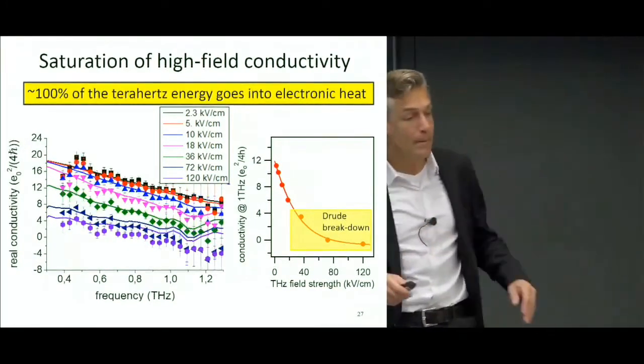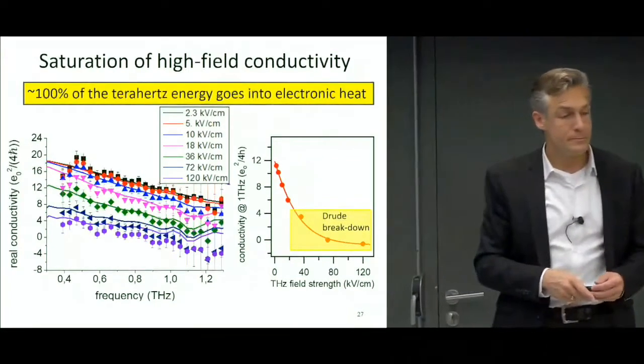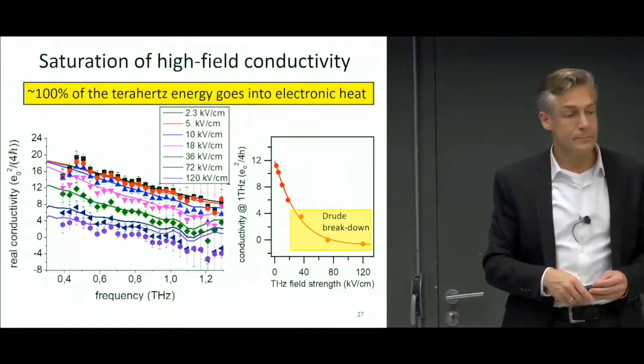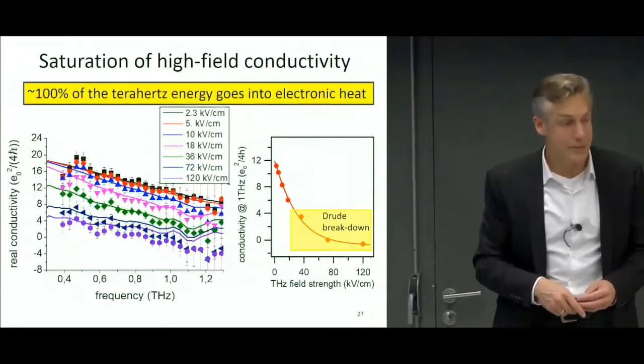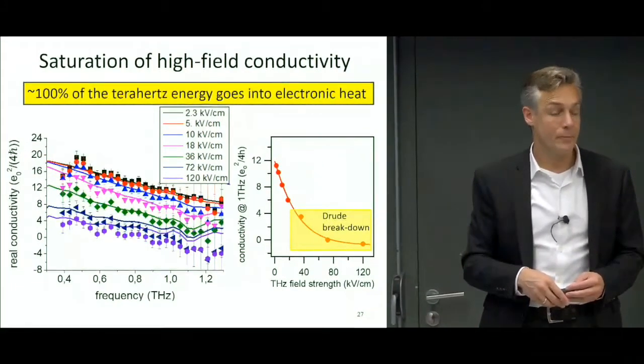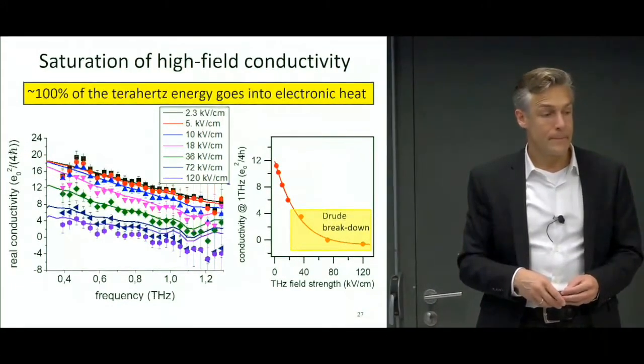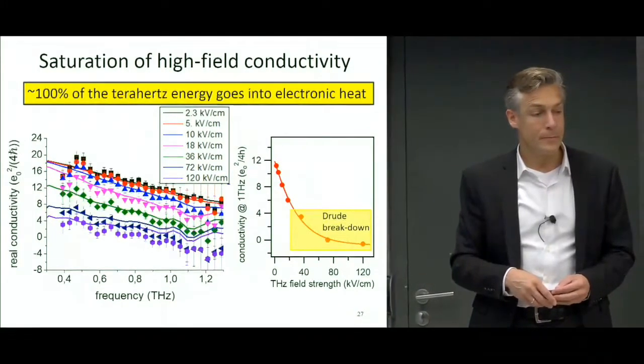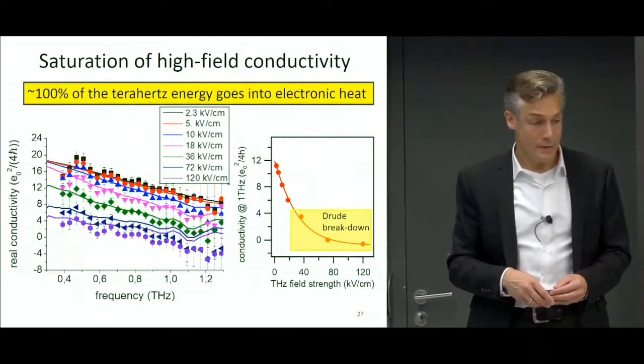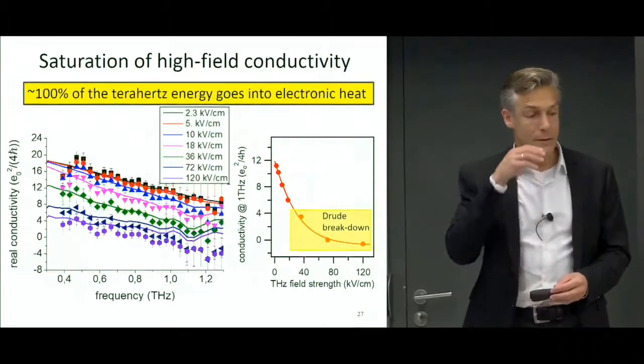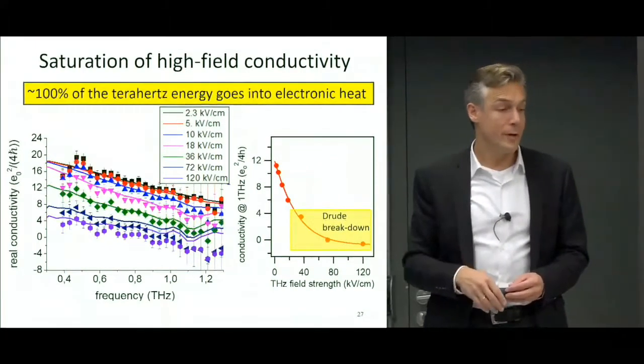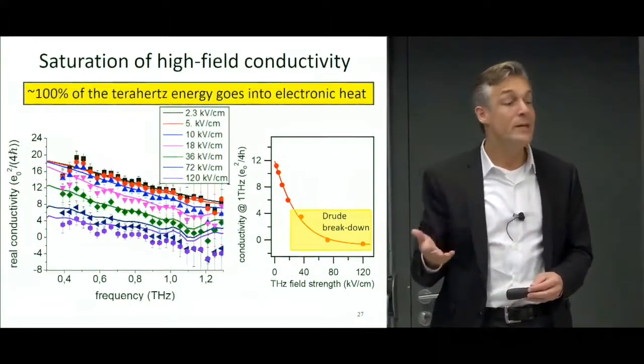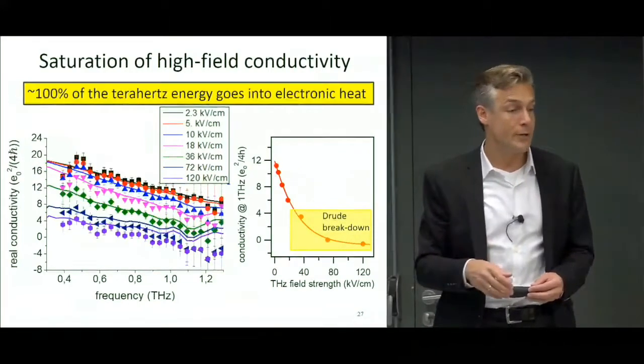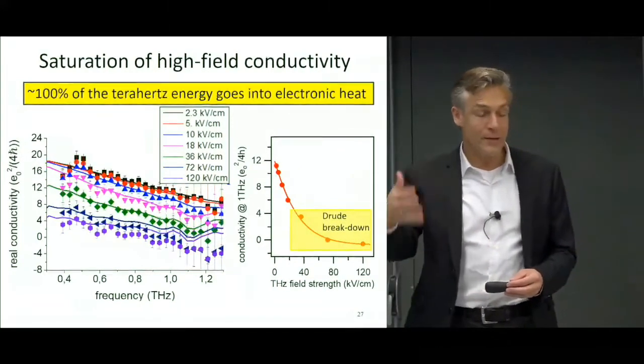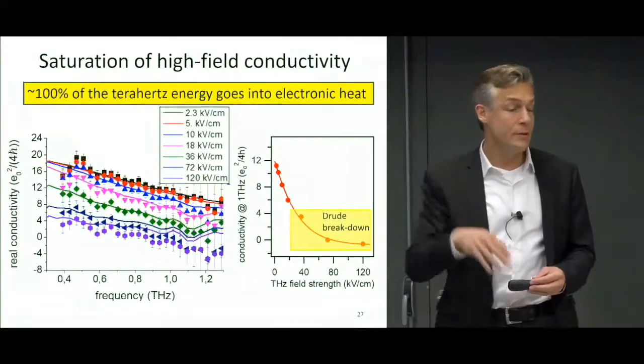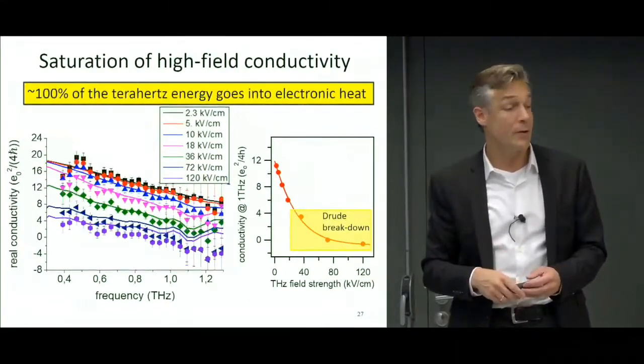Yes? So it means that you can basically replace the electric field with an effective temperature. The effective temperature controls. Exactly. And how hot is it? So it's thousands of Kelvin. And the reason for that is that the specific heat of the electrons is very low. So with relatively little energy, you can heat the electron bath a lot.